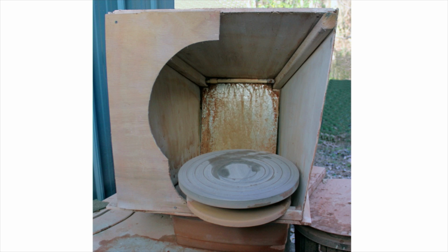I love to spray my glazes, so to collect and reclaim all the overspray, I built this spray booth with a large squirrel cage blower in the back to draw the air out, and a PVC pipe in the upper back with holes that creates a stream of water flowing down the metal back plate to catch the overspray and wash all the glaze materials down into a bucket of water below, with a simple pump to recirculate the water.